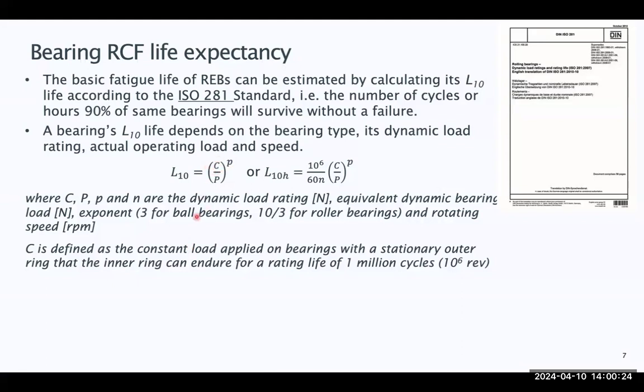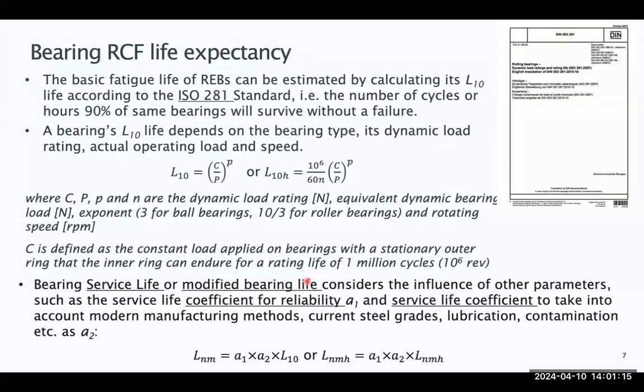The dynamic load rating is tested with a bearing that has a stationary outer ring, and the inner ring endures a load until failure at the rating life of 1 million cycles. So if the bearing can survive up to 1 million cycles under a certain load, then that will be the rating load of this bearing. That's the C for each type of bearing. Essentially, if you know your bearing design, you can simply work out the expected life.